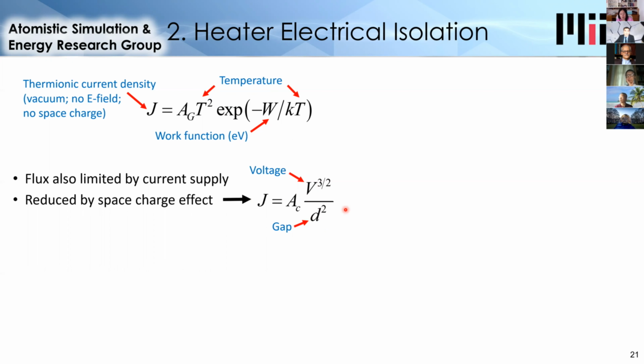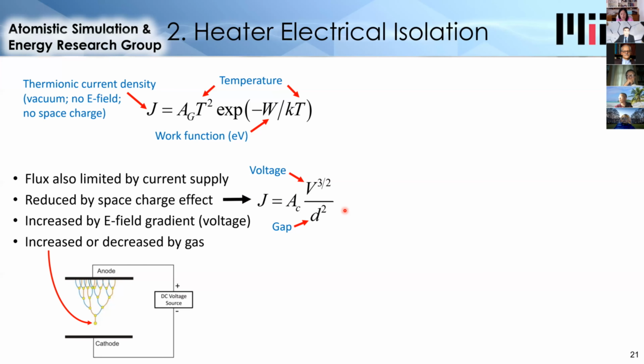And so the gas can act as an arc suppressant or an arc enabler, depending on the type of gas and the temperature. So one way the gas can cause more problems is if you get an avalanche effect where one electron is emitted, it hits a gas molecule and knocks off 2 or more electrons from that gas molecule. And so you can actually amplify the current in this way, causing a cascade breakdown, which is indicated by this figure here. So depending on the gas, the arcing can become better or worse.